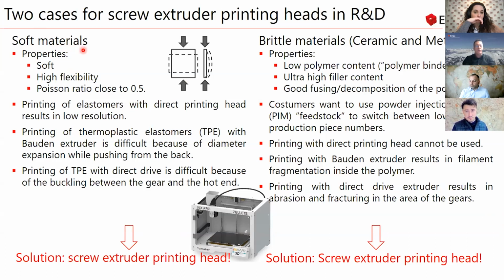When we look at soft materials, as the name says, these materials are soft and they have a high flexibility. Unfortunately, they also have a high Poisson ratio, which is close to 0.5. And that means when I push from the top, then typically the material is bulging. And by this, for example, it will block directly inside the Bowden extruder. Another problem is when you work with a direct drive and you push from the top, you have this kind of buckling here.